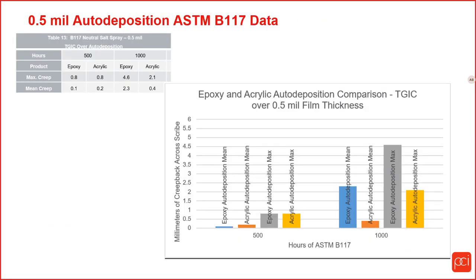As far as the testing is concerned, at 0.5 mil auto deposition, you can see that at 500 hour salt spray, the acrylic and epoxy were similar in results, where at the 1,000 hour salt spray, the acrylic showed better performance over the epoxy auto deposition.